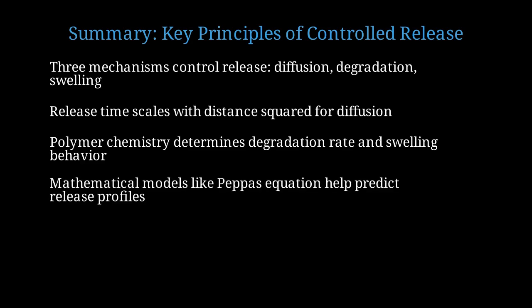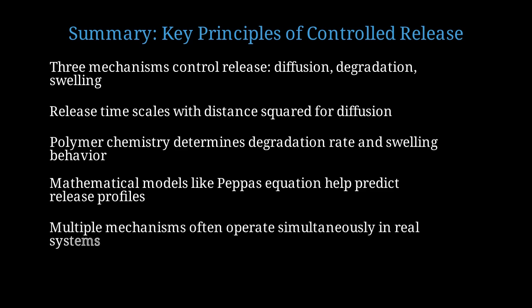The choice of polymer is critical. Polymer molecular weight, composition, and cross-link density determine degradation rates and swelling responses that directly control release kinetics. Semi-empirical models like the Peppas power law equation allow us to characterize release mechanisms and predict behavior. The release exponent n is diagnostic of the controlling mechanism. In practice, multiple mechanisms operate together, creating complex release profiles. Understanding these interactions is essential for rational design of drug delivery systems.